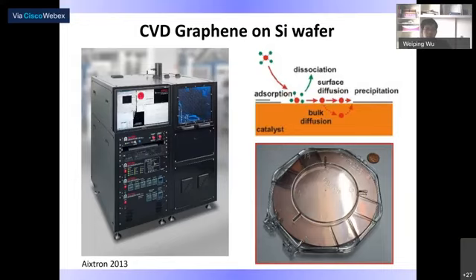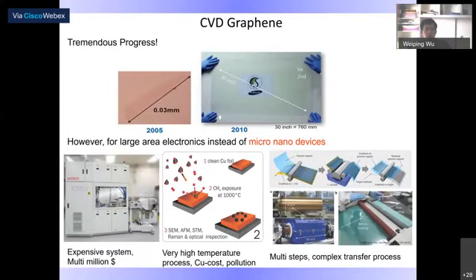This slide shows the facility developed by the company Aixtron that worked closely with Cambridge University. Samsung and these companies have been working from very early years on CVD graphene, scaling up very dramatically towards 30 inches. This process needs a transfer of the graphene electrodes from the copper, which serves as a catalyst. Therefore, we still can't see a lot of practical use even with CVD graphene. There are some demos from Samsung, for touch screens or OLED electrodes, but I think this process is quite expensive and it might be very challenging to get flexible electrodes at a low cost.